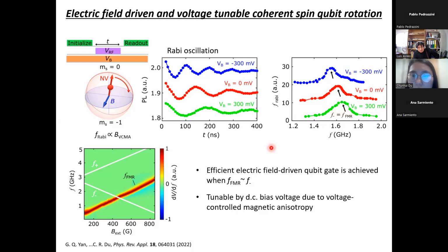So there is a magnetic field window where we can operate the device, and we can also make this operational frequency wider by adding a bias voltage, because it changes the anisotropy of the system. So it changes the FMR dispersion, and changes where the FMR crosses with the NV-ESR. So basically we can further control the Rabi oscillation electrically. I see. Okay. Good. Thank you.